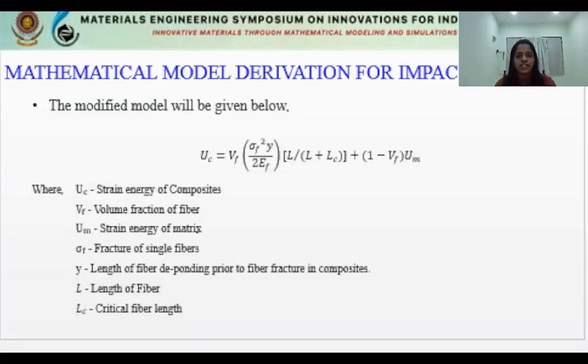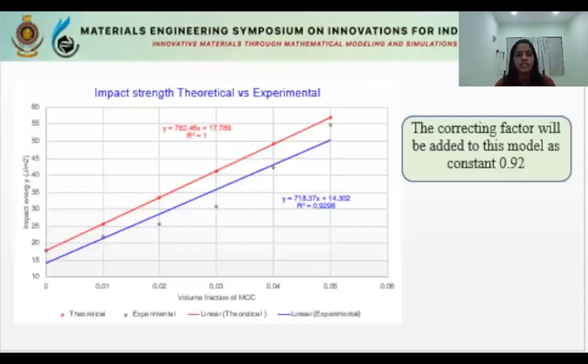Go to the next slide. Impact strength experimental values were less than the theoretical values, as expected. Almost all are aligned with the experimental values, and the correction factor is 0.92.